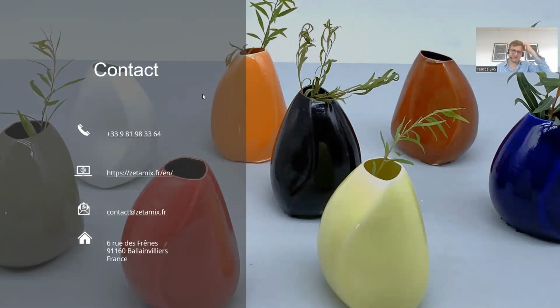Is it possible to soften and polish a surface before glazing to glaze only some areas? Of course, it's possible. For me, the simplest would probably be to polish after the first firing, because you'll have something that behaves very nicely from that perspective, and you can polish it very well. You could also polish it before debinding. Both of them work. If you're happy with the glaze look, glazing will do the work for you, so you don't have to manually polish anything. Glazing will smooth it out. But of course, if you want to glaze only specific areas and have an unglazed surface, that's a possibility.